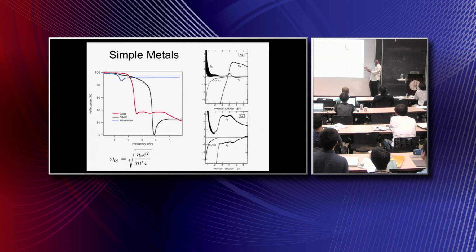I mean, it's a bit of a mystery, right? Why should gold and silver look so different? They have about the same Fermi surface. Their densities are about the same. And the reason is because there's this large extra amount of absorption for deeper energy levels in gold that ends up making this sharp edge here, which we call the plasma frequency, at much lower frequencies.